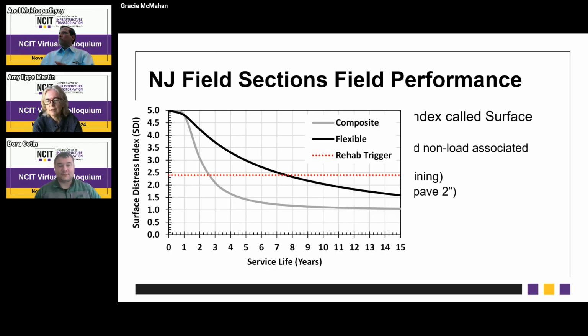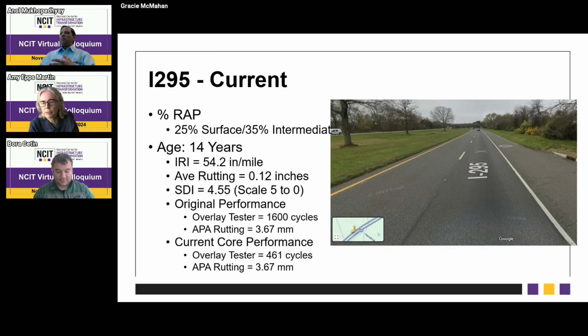Next slide, please. So just to quickly step through, this is a 14-year-old pavement, and it still has pretty good performance. You can see the original performance was very, very good on the overlay tester. I think the requirements are in the 200 to 300s, and it was at 1600. And even after 14 years, it's still meeting that cracking requirement on the overlay tester and the rutting requirements from the asphalt pavement analyzer. You can see also that that surface distress index is still very high, and you can see from the picture that it's in good condition.